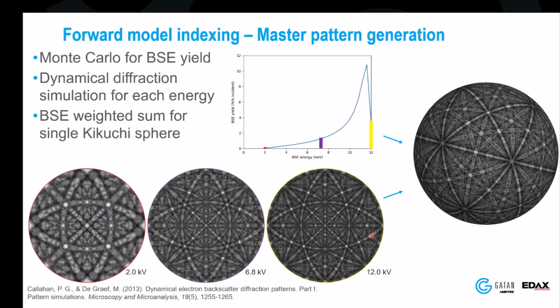And this, depending on your materials, can be relatively quick. Some FCC materials take like 5 or 6 minutes on most computers, and some of the lower symmetry materials can be quite long. And again, that's one of the downsides of the older dictionary methods. You'd have to redo these master patterns depending on the conditions.